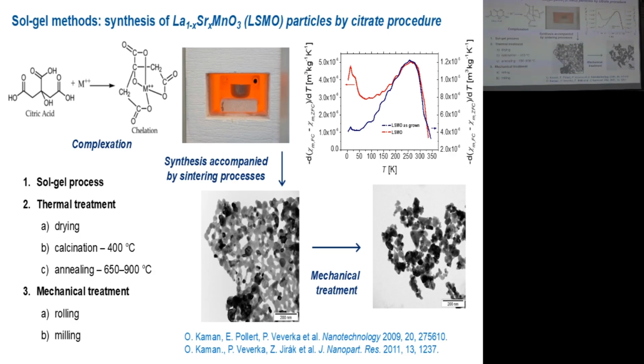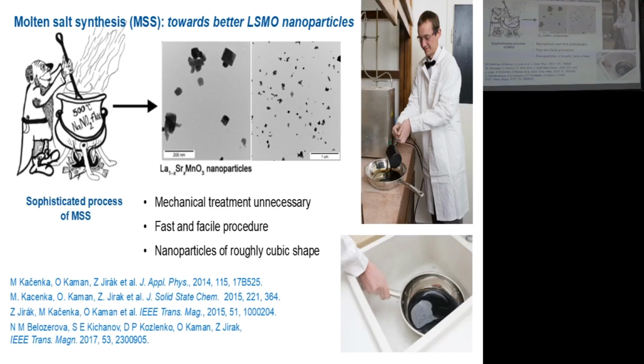Maybe the size distribution of these particles is also large, but we achieved well dispersed or partially dispersed particles of predominantly cubic shape. We were very happy. It was a new synthesis, quite tricky in terms of manipulation, because we were using a large volume of molten sodium nitrate, or in certain experiments also sodium nitrate, which is, you know, not very compatible with organic stuff. If you mix a strong oxidizing reagent in molten form with some organic stuff, it may cause big troubles. But it was something new.